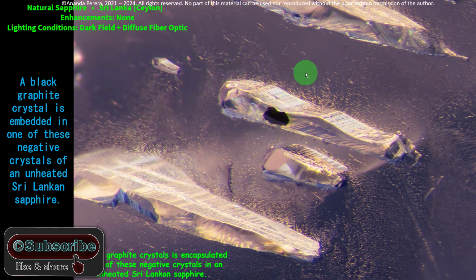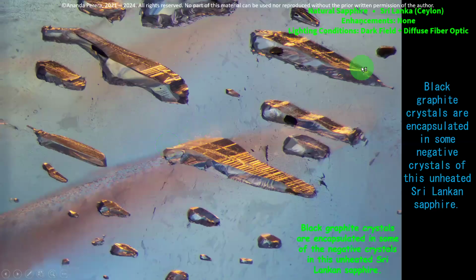See the very small negative crystals inside the fingerprint. These are the big ones. Dark field illumination and diffuse fiber optic is the lighting condition used here. Here, what is the lighting condition? The same: dark field plus diffuse fiber optic. You can see very nice negative crystals, and the black dots are the graphite crystals. The black graphite crystals are encapsulated in some negative crystals of this unheated Sri Lankan sapphire. So it proves it is unheated.